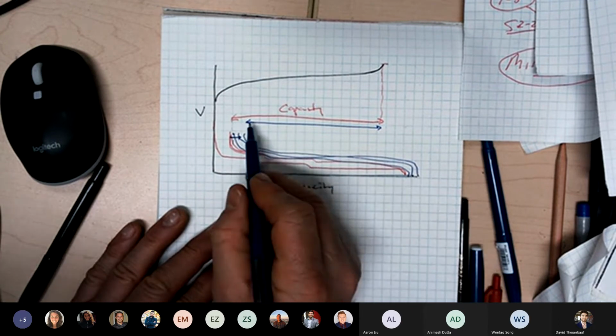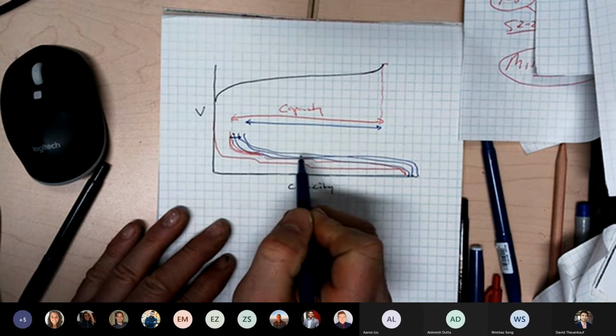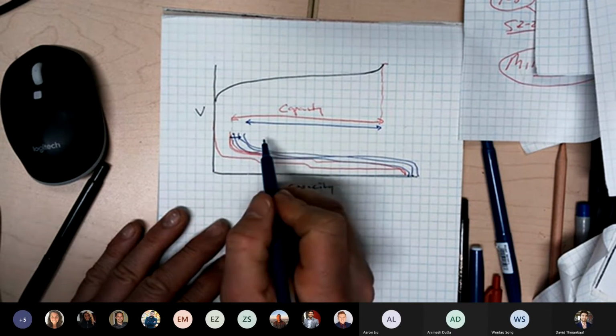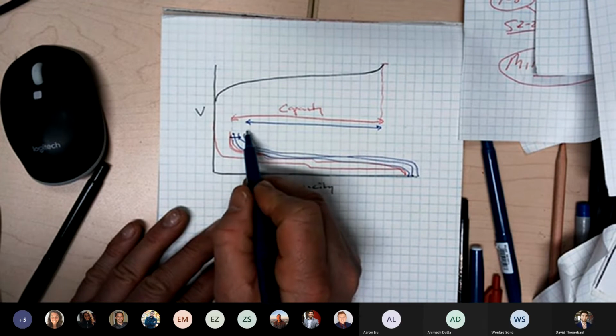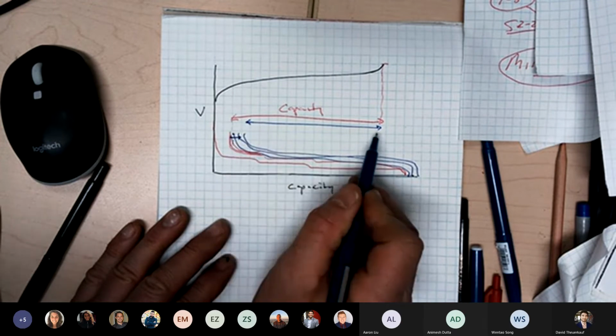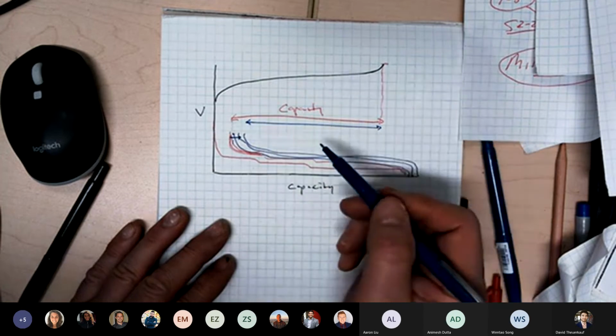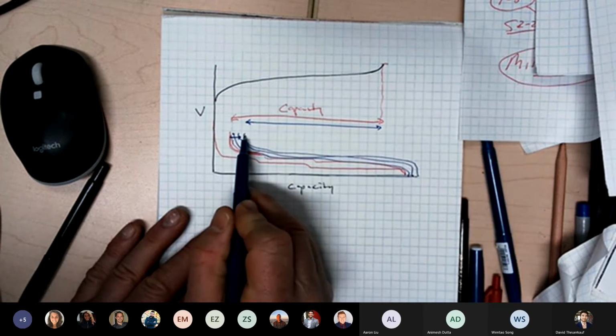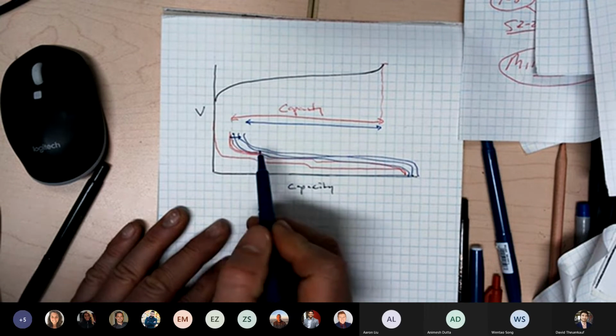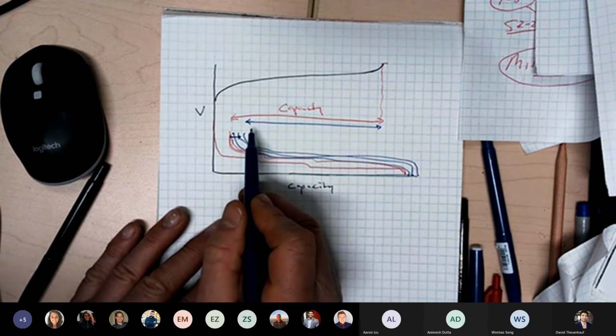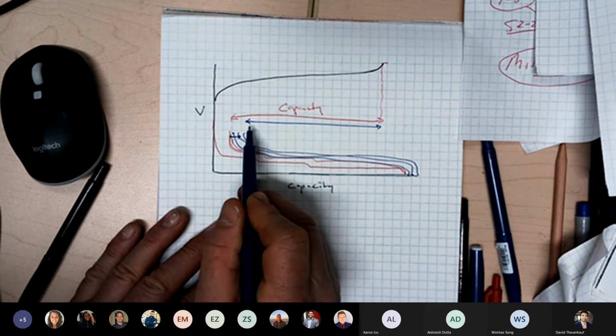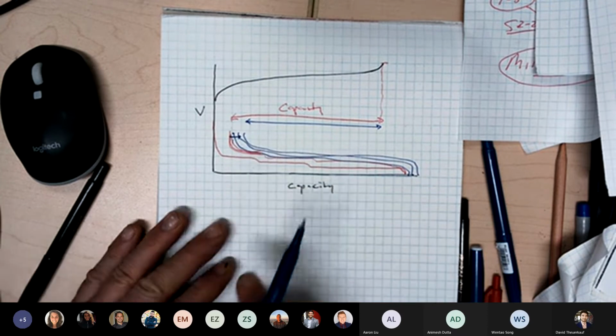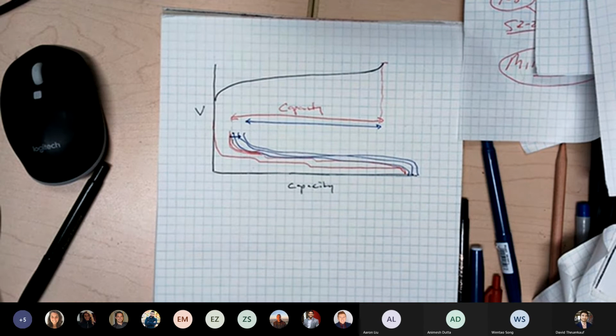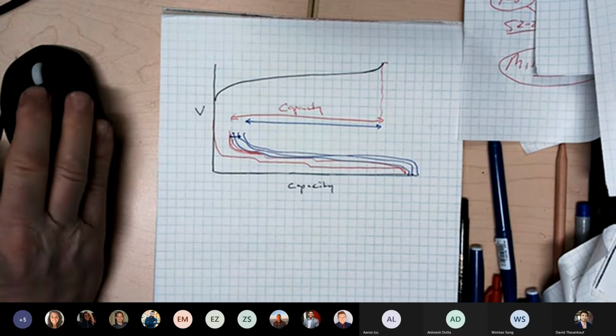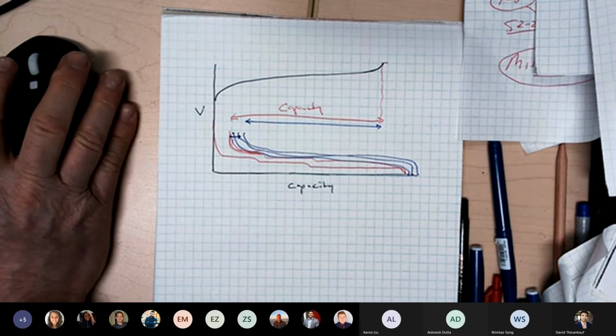So if you just plot cell capacity versus cycle number, which is proportional to time, or versus time, you will see a decrease in capacity, provided there's nothing else bad happening in a cell. The only capacity loss mechanism is SEI growth on the negative side. And at elevated temperature, like 40 degrees C and above, this is by far the dominant capacity loss mechanism in lithium-ion cells that only have a graphite negative, no silicon or fancy stuff.